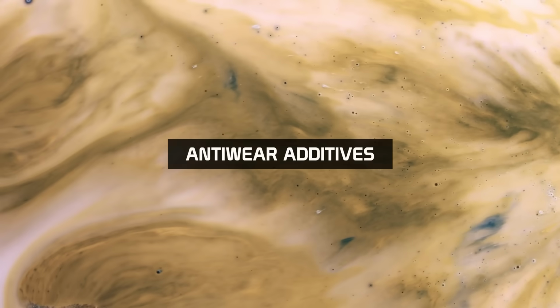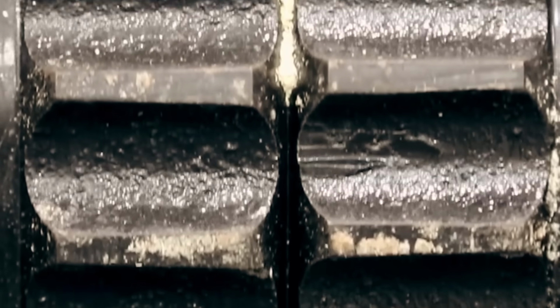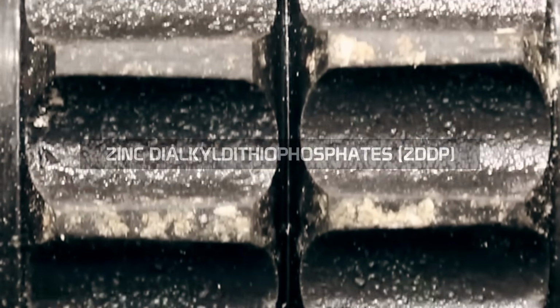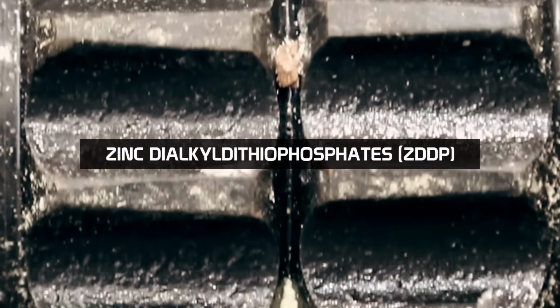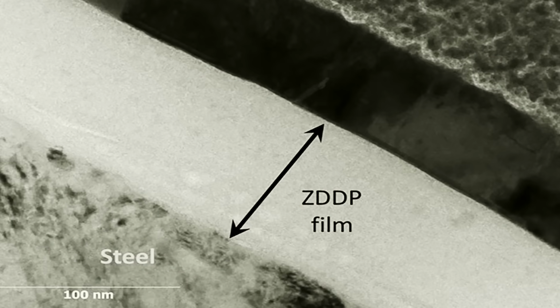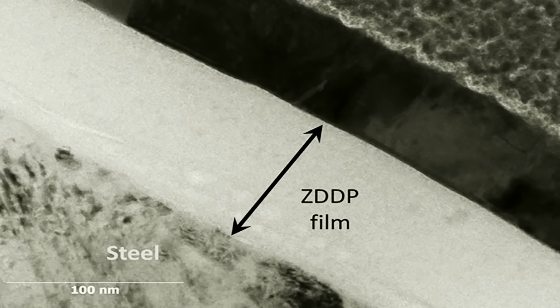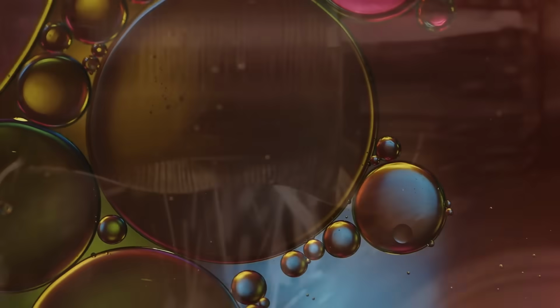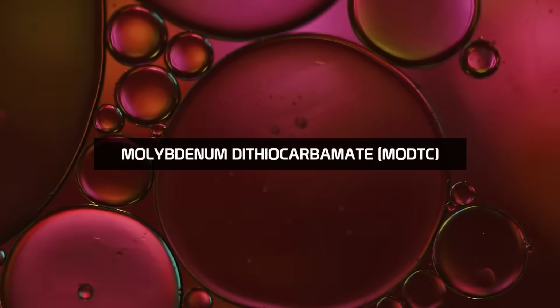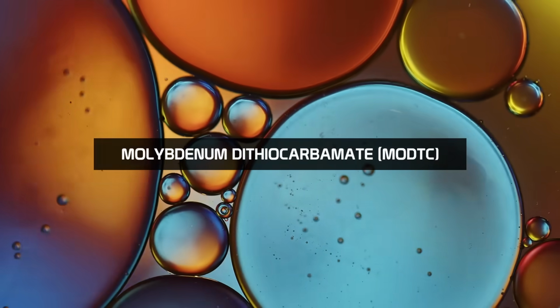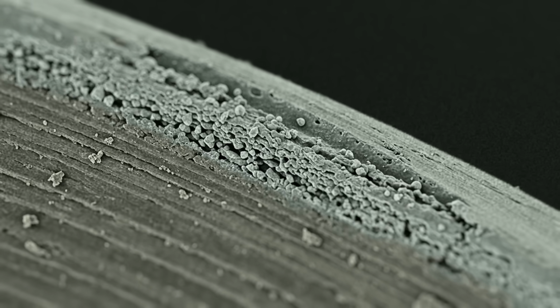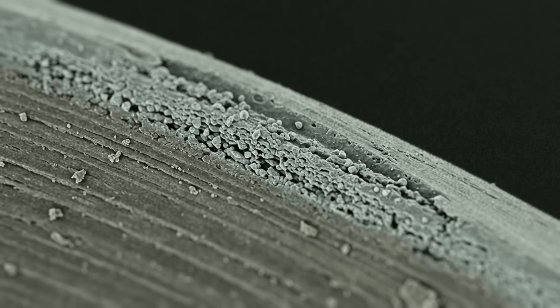Anti-wear additives are another common addition to oil blends and are primarily used to protect the engine during boundary lubrication conditions. When a full oil film cannot be maintained, one common additive, zinc dialkyl dithiophosphate, or ZDDP, for example, decomposes under heat and pressure to form a sacrificial glass-like phosphate film on metal surfaces. For more severe conditions, with extremely high loads such as in gear oils, extreme pressure, or EP, additives are required. These compounds, often containing sulfur-phosphorus chemistry or organometal compounds like molybdenum dithiocarbamate, or MoDTC, react chemically with the metal surfaces only at the point of intense pressure, forming a resilient boundary layer that prevents welding and scuffing.